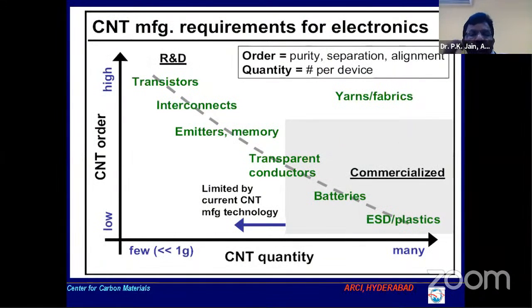The cost of carbon nanotube is always very controversial. Some people say we are getting it at $100 per kilogram. Some people say $10,000 per kilogram. How the cost comes into the picture depends on the processing, the application, and the order of the CNTs; the quality of CNTs will decide the cost. If you go for a very low end application like plastics or tires, by adding 1% or 5% of carbon nanotube, the volume is very high, so one can get very low cost nanotubes, which are not of a very high order. But if you go for very high order carbon nanotubes, used in electronic industries like transistors or interconnects, the cost is very, very high.